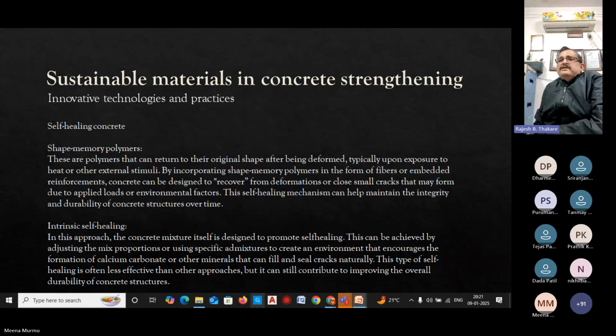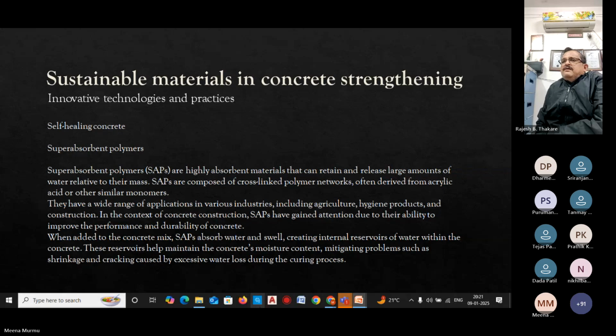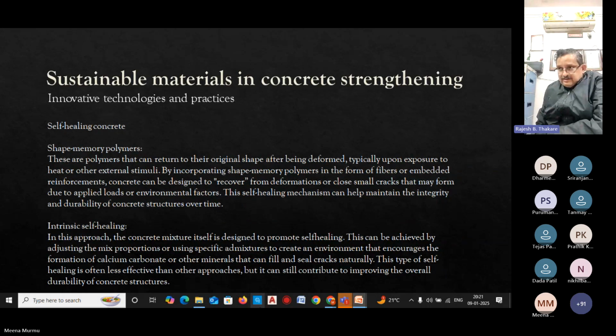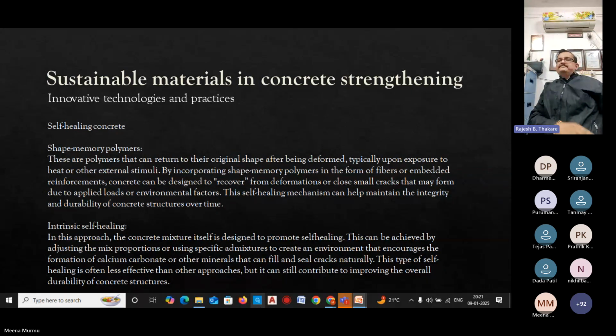Then intrinsic self-healing. In this approach, the concrete mixture itself is designed to promote self-healing. This can be achieved by adjusting mix proportions or using specific admixtures to create an environment that encourages the formation of secondary calcium carbonate or other material which can fill and seal the cracks naturally. This type of healing is often less effective than other approaches, but it can still contribute to improving the overall durability of concrete structures.